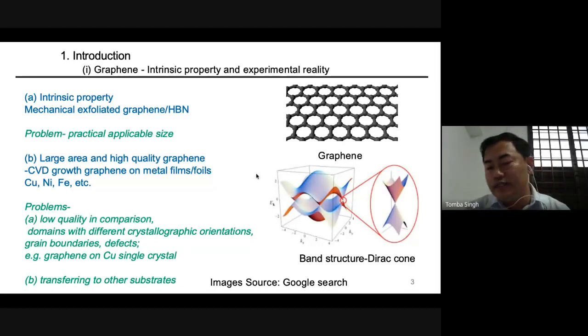So from where do these interesting properties of graphene arise? If we look at the graphene structure, we see 6 carbon atoms in the hexagon. Out of this, we can make 2 triangles. Triangular sublattices are there. If we rotate 120 degrees, we can get another triangular sublattice. They are equivalent. If we look at the band structure, that is the Brillouin zone of the graphene, this Brillouin zone is also hexagonal, similar to the structure.